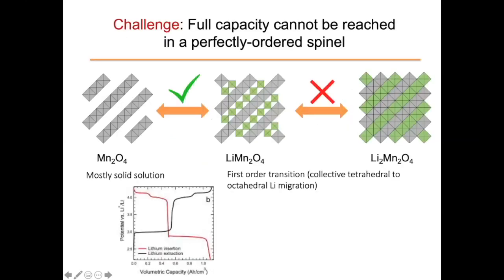But there are problems with spinel, right? In the 90s, we all tried to use spinel for batteries, and that field is sort of dead. And the reason is the following: one can easily cycle spinel between LiMn2O4 and Mn2O4. This is mostly a solid solution. There are some minor phase transitions there. But this only gives you 140 milliamperes per gram.